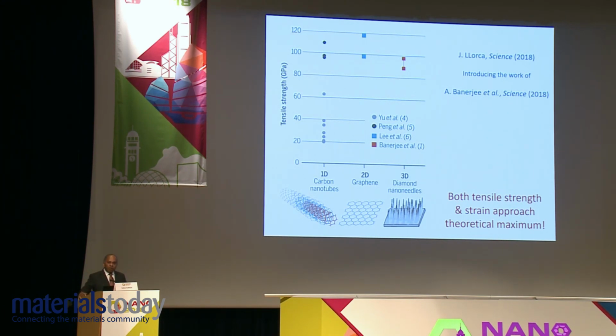It is being thought that the minimum strain that you need to achieve this is of the order of 6 to 7% tensile strain. And we show here that in certain cases, you may be able to achieve as high as 9% strain. So this is yet another area where there is a lot of opportunity to explore possibilities in diamond with phenomena that one sees only at the nanoscale.